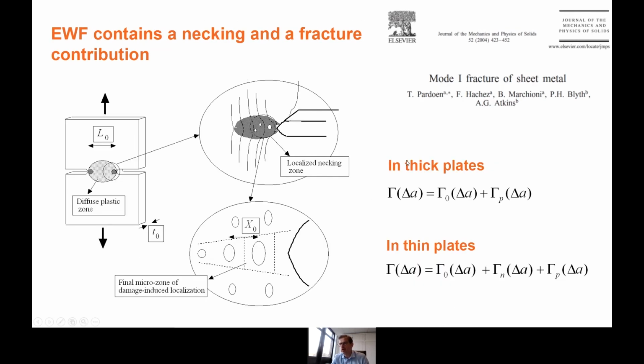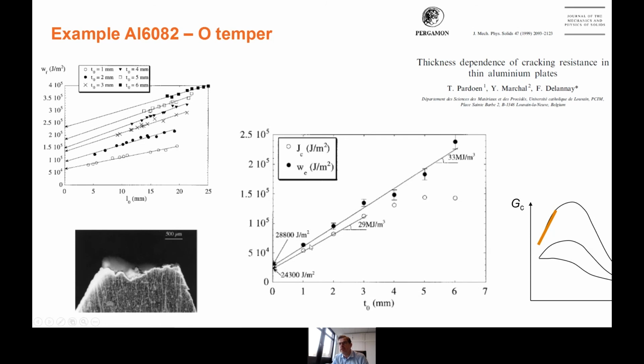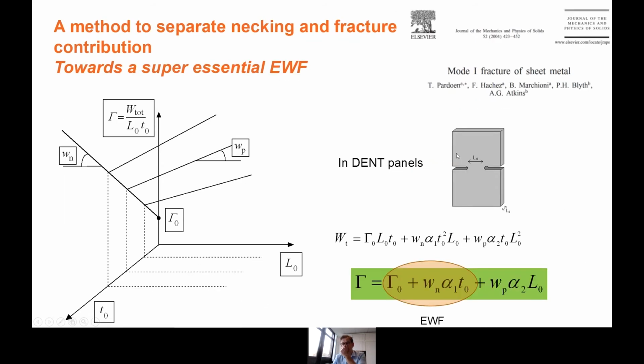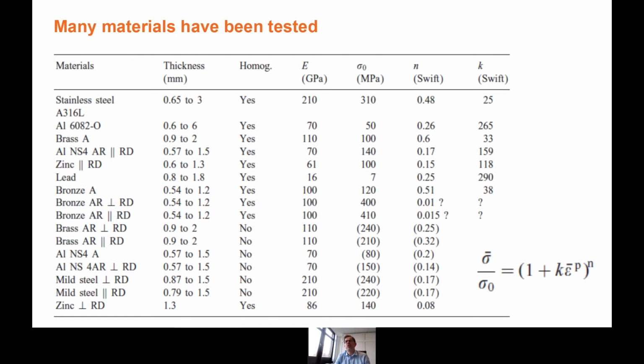So by the way, look back at the result I've already shown before. You see that the essential work of fracture increases linearly with thickness, and that there is a constant term, and this term is the gamma 0, and the extra term here is the work of necking. Can we go deeper and try to put numbers on the work of necking and relate it to other quantities? So we tested at that time many materials, and as a matter of fact, these materials were coming from Tony Atkins, and he wanted to look at these materials from an archaeometallurgy viewpoint. So we worked with all these materials.